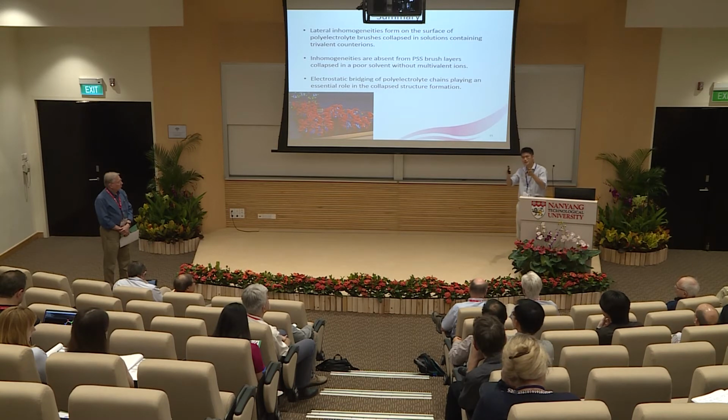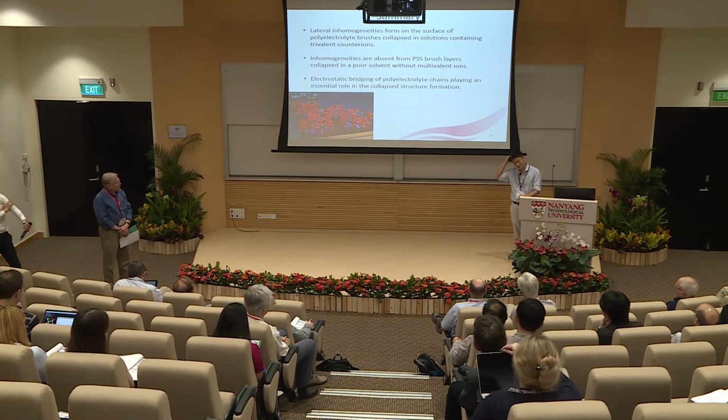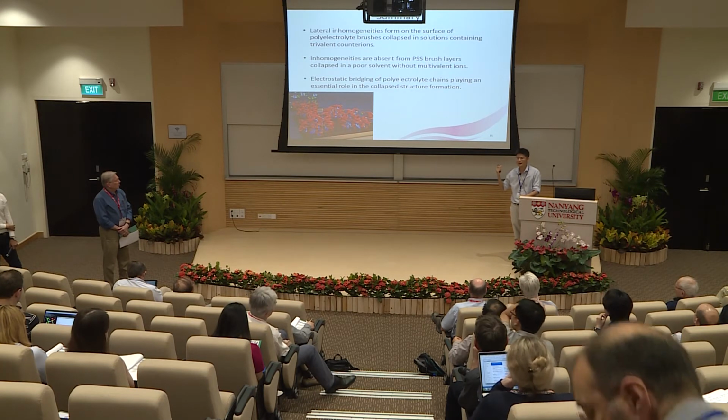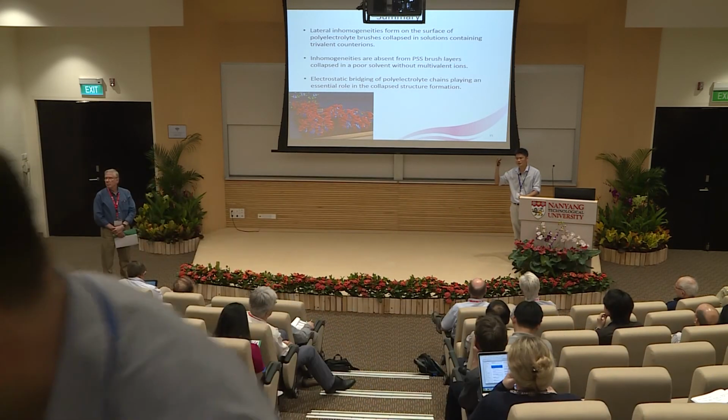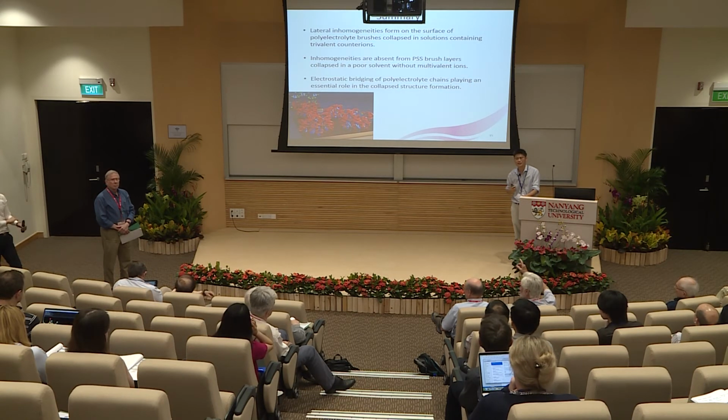Well, certainly, the electrostatic repulsion is especially important when you have low ionic strength. When you increase the ionic strength, the Debye length decreases, and then it becomes less significant. Another thing we noticed is that in this particular case, the Debye length is close to the fluctuation range of the polyelectrolyte chains. Therefore, we believe the two are convoluted and it's really difficult to separate them in some circumstances.